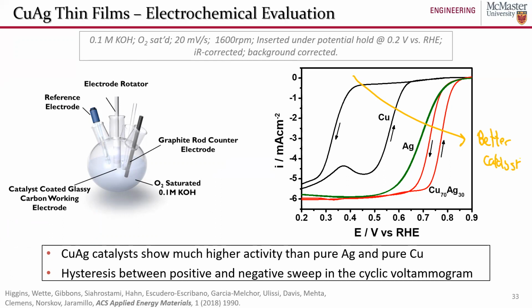And so from just looking at this plot, you can see that copper silver was our best catalyst, silver was our second best, and copper was our third best. And it was interesting to us that the mixture of copper and silver performed much better than silver, a well-known ORR catalyst, and much better than copper. So these two things were not operating like the sum of their parts. They were coming together and providing a significant boost in activity, and we weren't sure why.